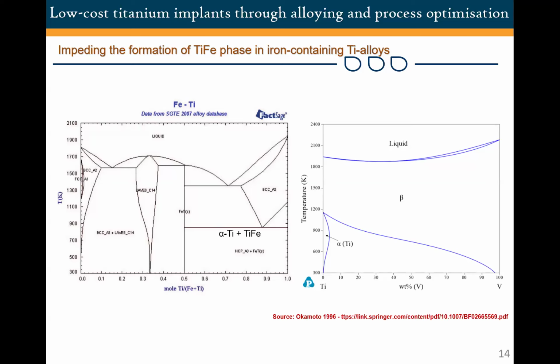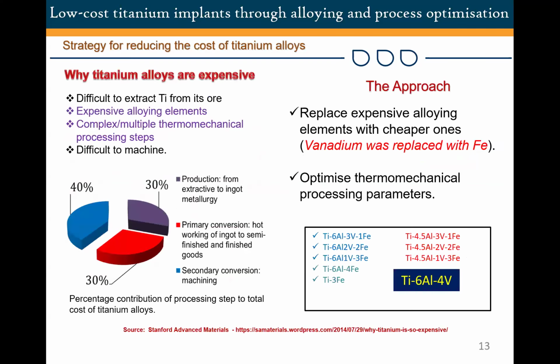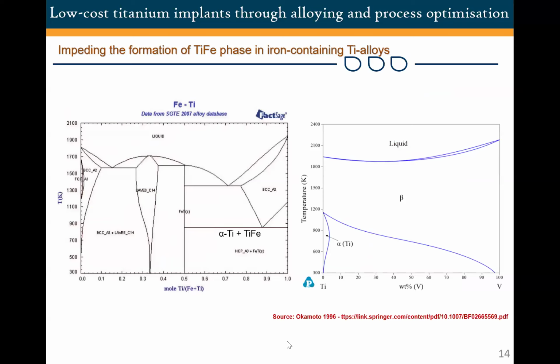But that doesn't really give you the type of properties that you would desire when making, for example, components that would be put in human bodies. So with vanadium, you don't have this problem of intermetallic phase. So our idea is, rather than doing what everyone has done, let's have partial substitution of vanadium with iron. So if we go back, you would see that the compositions that we've explored mostly here have partial replacement of vanadium with iron. And what we realized is that we were able to actually suppress the formation of this TiFe by retaining some vanadium in that composition.